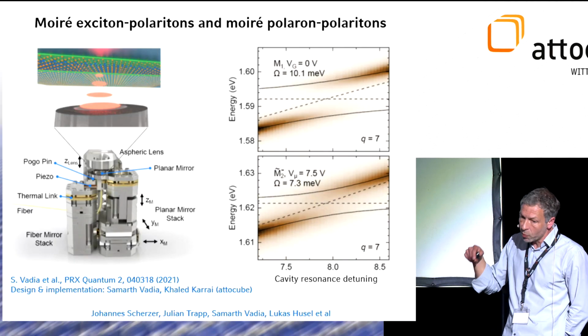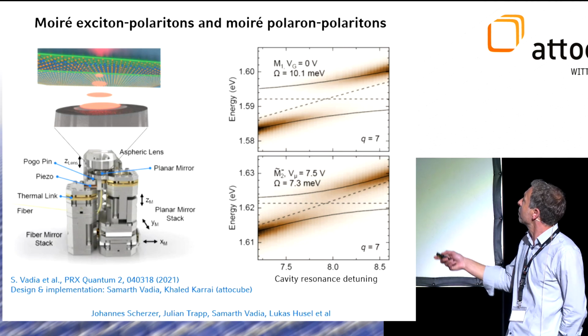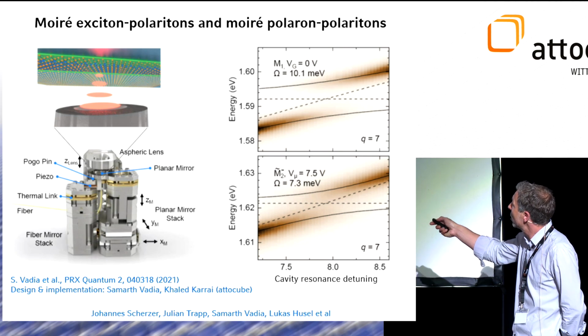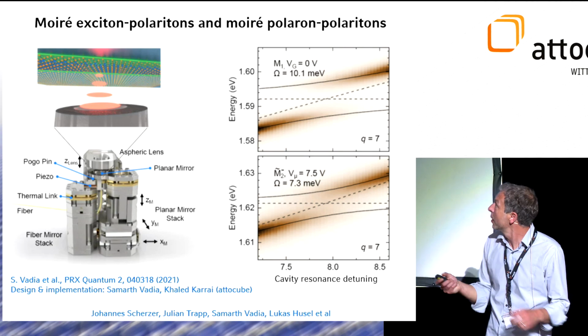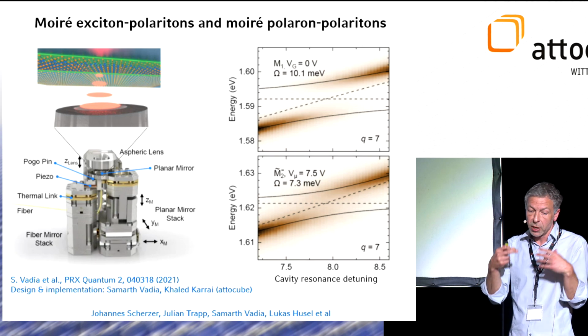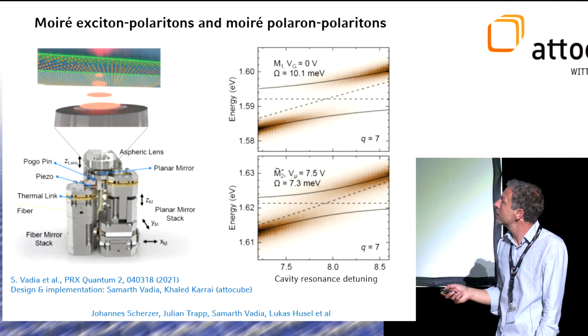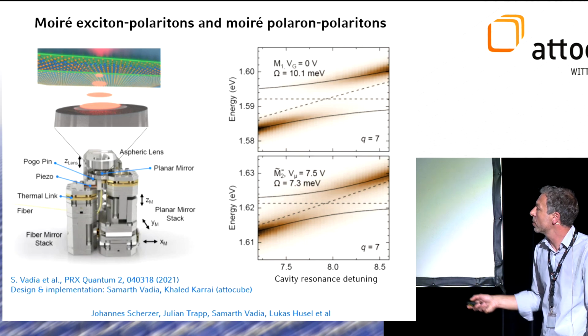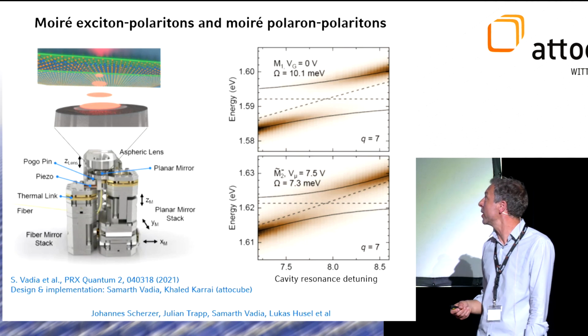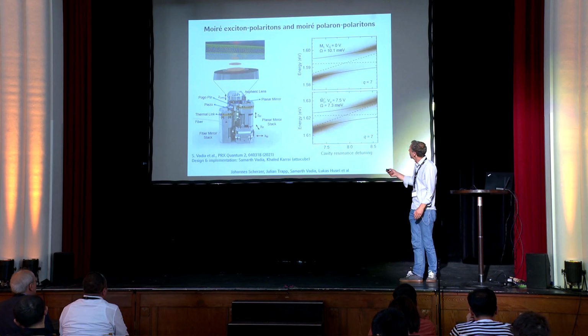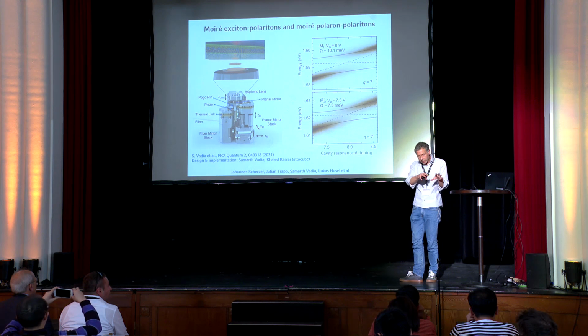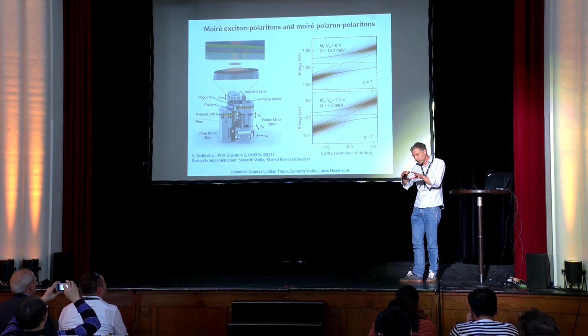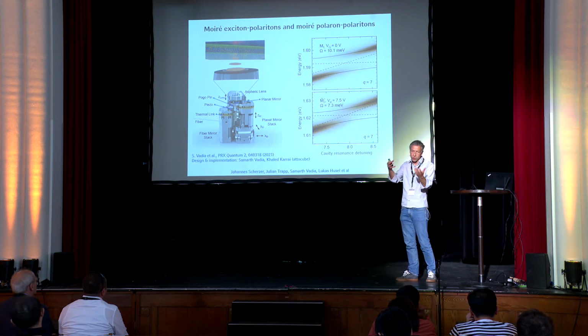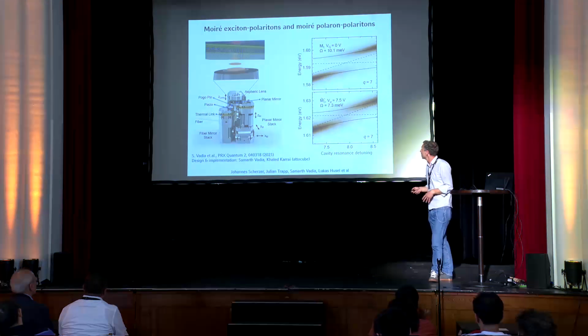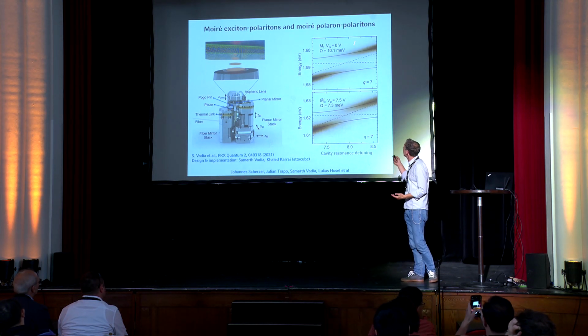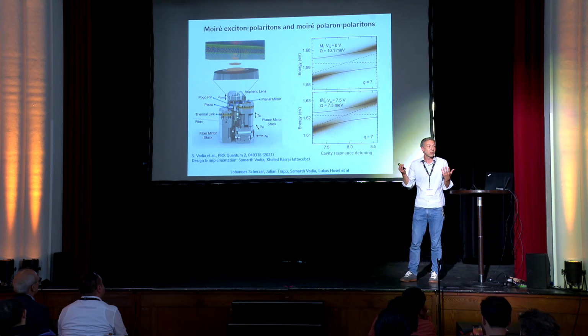It's a moiré system in an open cavity subjected to charging. So in the neutral regime and in the charged regime, we see that both excitons, M1 and M2 charged, can couple strongly to a cavity. I should point out that this open cavity has been realized together with Khaled Karrai, so it's a brilliant piece of instrumentation where we can now map the magnetism of the spin lattice onto the moiré exciton and couple this into a hybrid mode, hybridize it with a photon, realizing moiré exciton-polaritons with signatures of correlated magnetism.